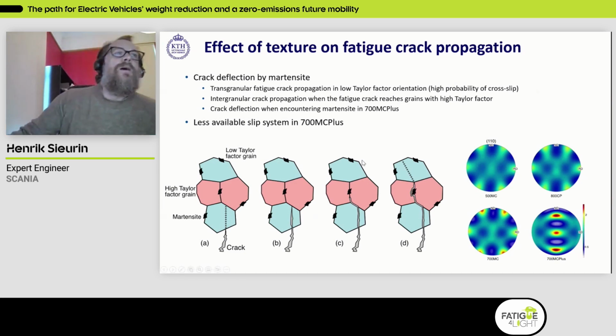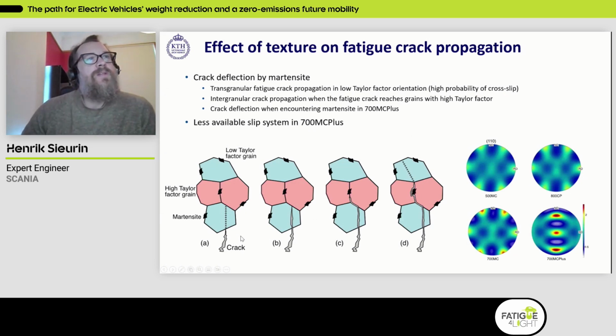First, if you look at the crack propagation in this material, we have a combination of transgranular and intergranular crack propagation. So the crack propagates transgranular with grains with a low Taylor factor, and then it starts to grow intergranular in grains with a higher Taylor factor. And in addition to this, this material also has martensite on the grain boundaries. So there the crack has to, again, propagate intergranular, also around this martensite on the grain boundaries.